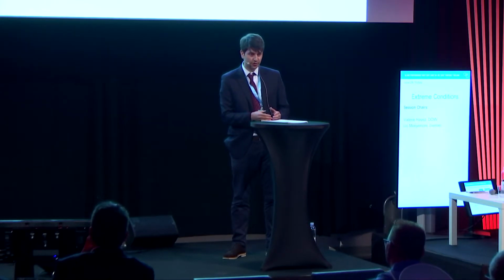It was also noted in these tests that the stress-strain response of the composite interlayer with attached glass fragments is elastic perfectly plastic, rather than elastic plastic with strain hardening as observed in the behavior of PVB alone without the attached glass fragments.